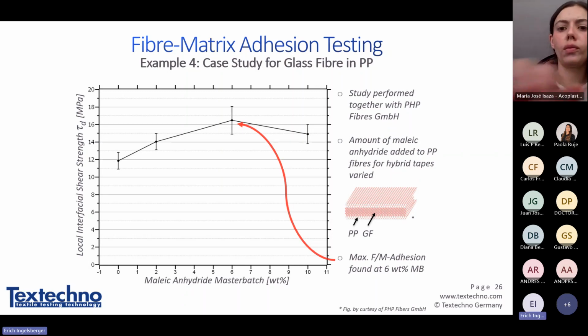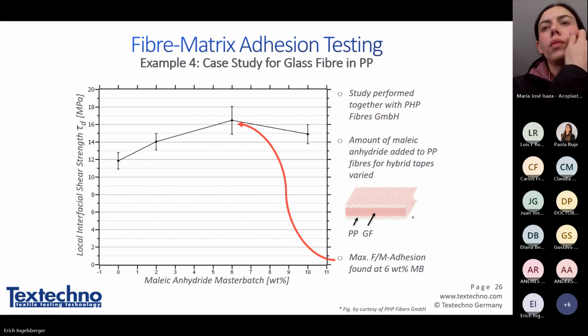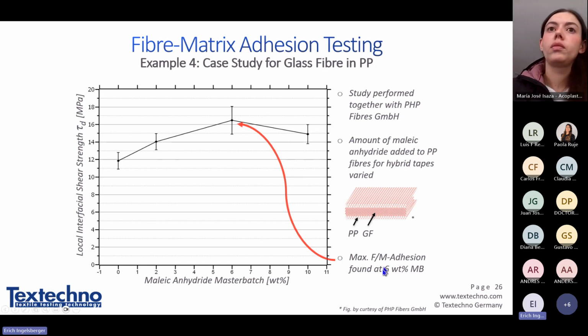This example shows the optimization of a matrix. What we have here are glass fibers, tape of glass fibers, embedded in polypropylene fiber. This is the matrix, and these are the reinforcement fibers. Then this will be pressed and melted. This study was made together with a German company, PHP fibers. They wanted to know at which weight amount of maleic anhydride added to the polypropylene fibers you would have the best fiber to matrix adhesion. This has been found at 6 weight percent of maleic anhydride.